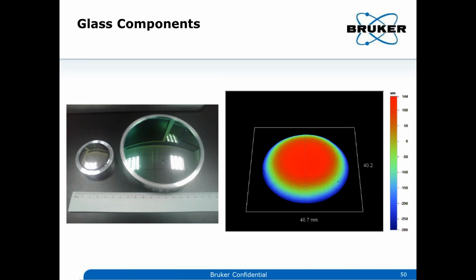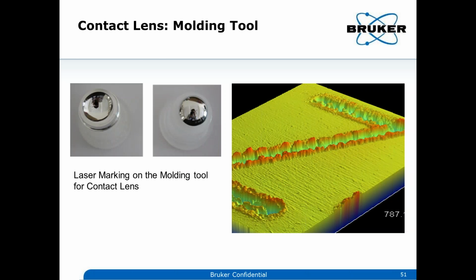Some glass components, for example, in projectors or things like that. You have these glass lenses, big ones, and you can measure. These are quite big, right? It's about 40 millimeters, very big lenses, and you can still see some fine features. If you look closely, you can also see the molding lines, and you can also see some pits and other faults in the glass. These are okay, but there are certain tolerances that need to be controlled, and we can measure that.